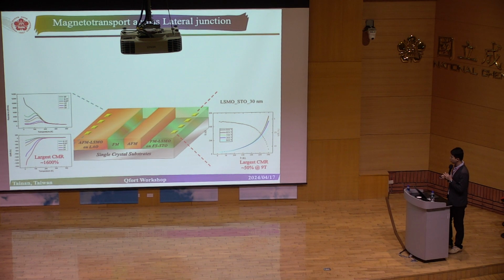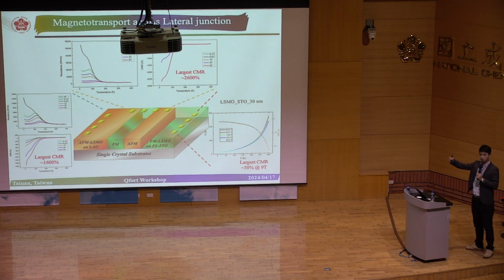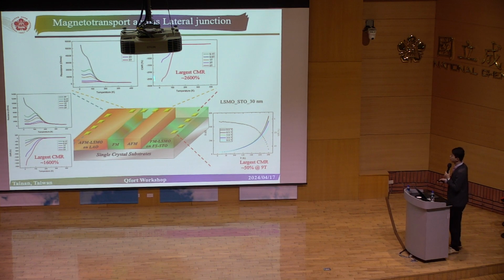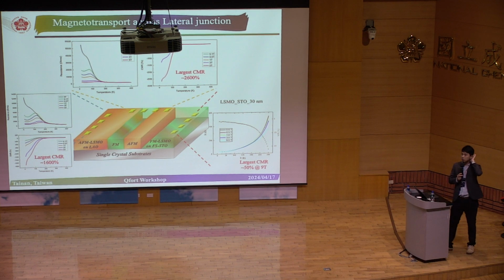So compared to the original CMR value, which is around 50%, here we can have 1,600%. Okay, so let's take a look at what essentially happens if you do something across the boundary. We do the same thing and get the magnetoresistance value. Now, the CMR value can reach as high as 2,600%. That means that by composing this kind of feature, we might take advantage of the interaction between the adjacent ferromagnetic layers. So let's take a look.